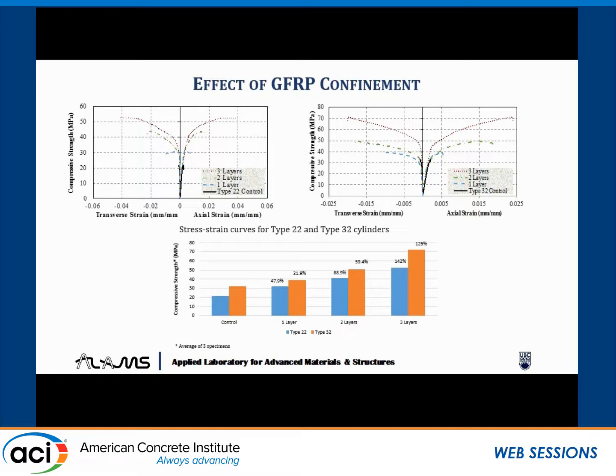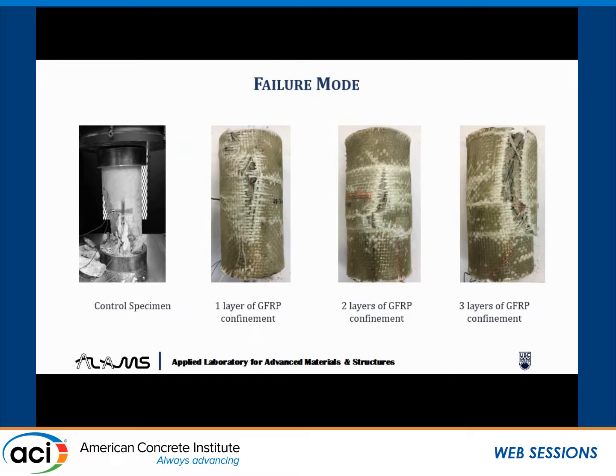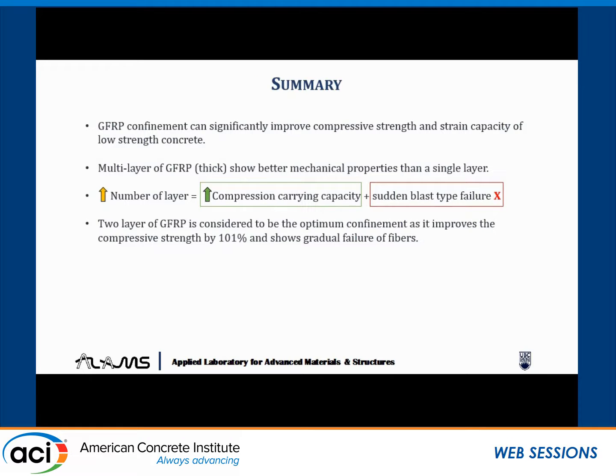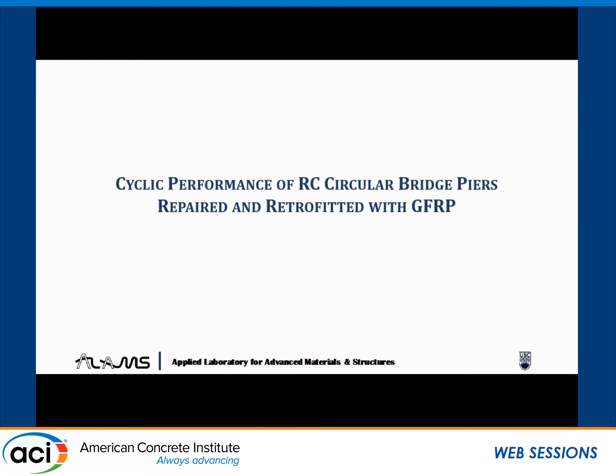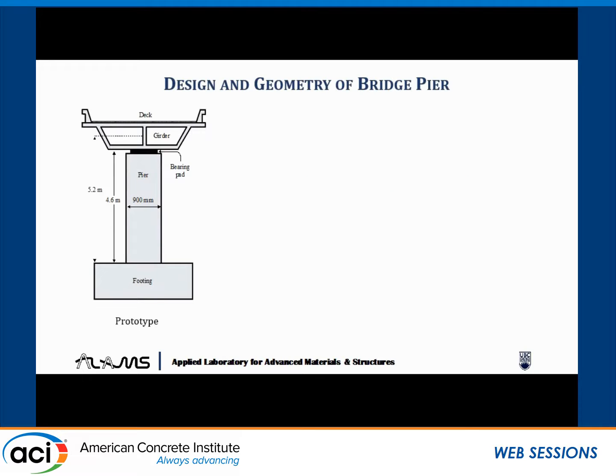If you look into the strength, this was the control for 22 and 32 MPa, and you get significant improvement with 2 layers and 3 layers. These are the failure modes that we observed. For 1 layer, there's a gradual rupture of FRP. But when you have 3 layers, there was sudden rupture, as you expect, and also distortion under compression. From the preliminary results, we found the mechanical strength, the overlap length, how they behave, and how many layers we can use. We found that 2 layers of GFRP should be optimum. And then we go to the reduced scale testing of bridge piers.